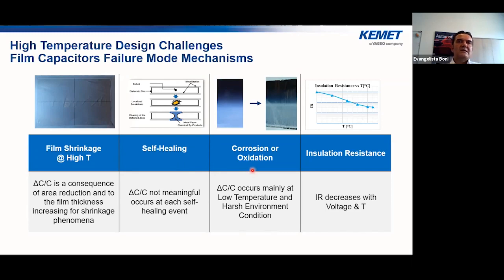Later on, we can see the third failure mechanism, the most important one, which we think is due to the corrosion and oxidation that can happen at high temperature, considering also some water content inside the capacitor. It's possible to see on the left the film beforehand, and at the end, the situation after an endurance test at 125 degrees on the standard series. It's possible to see that the metal is turned to oxide, and for this reason it is possible to observe a capacitance drop, but also a dissipation factor increase.